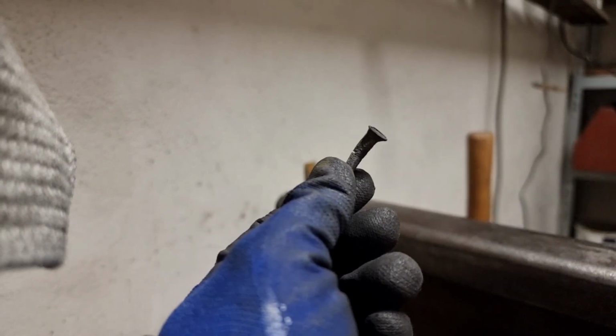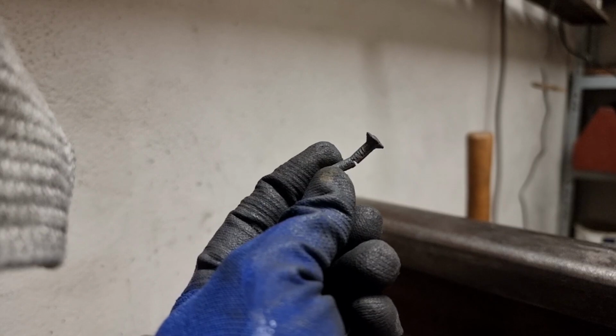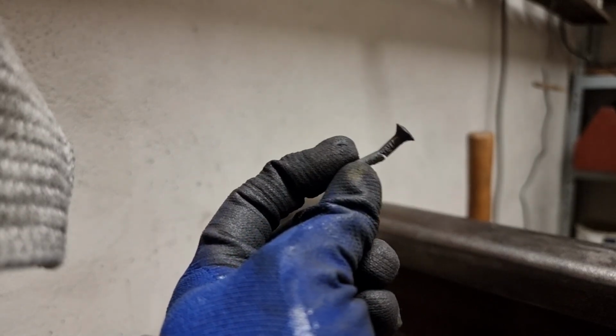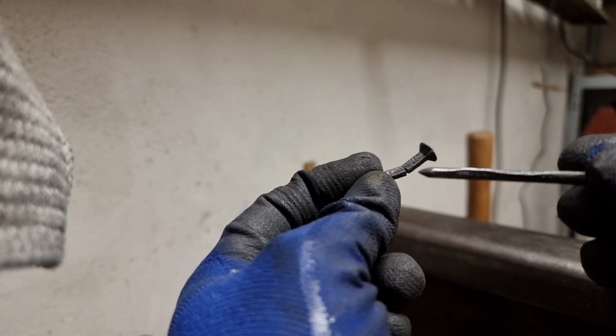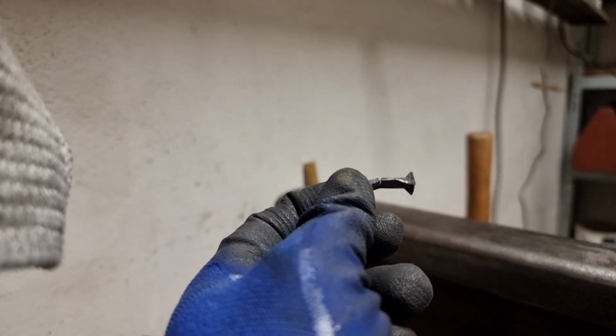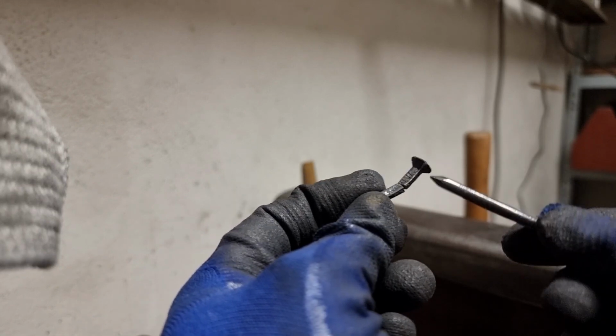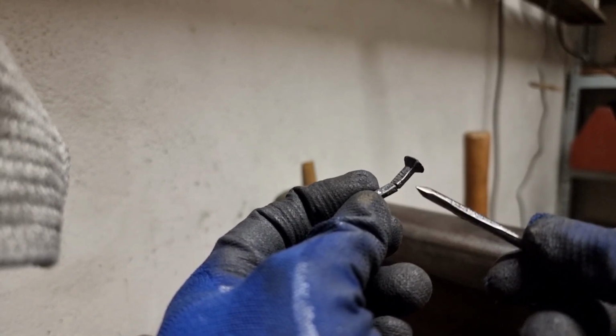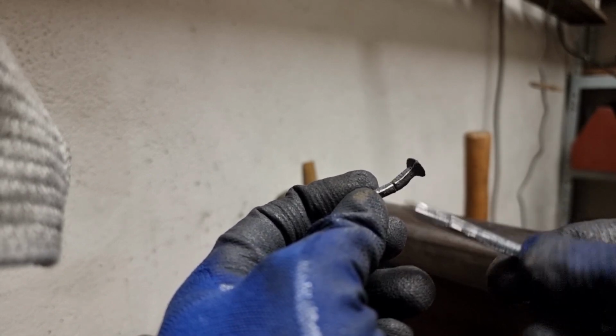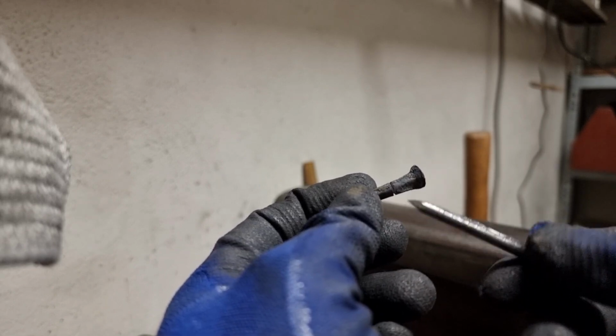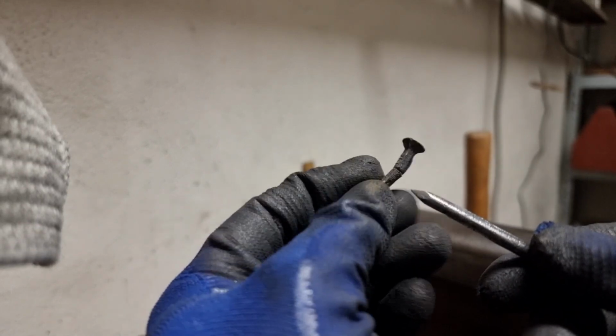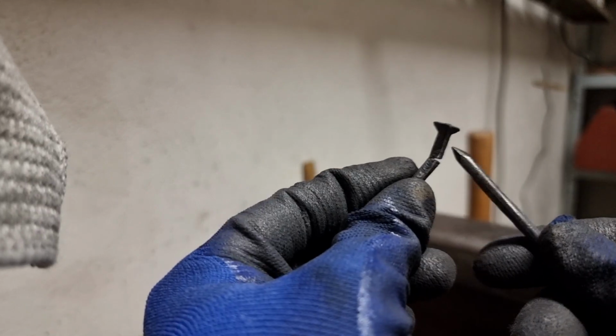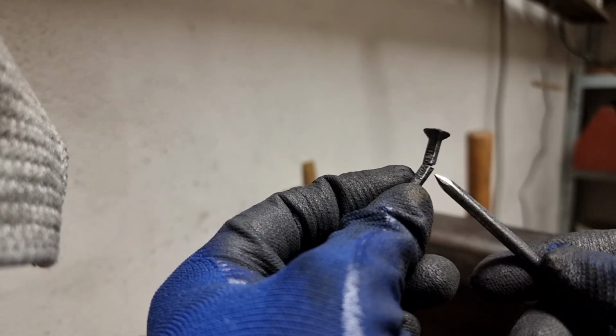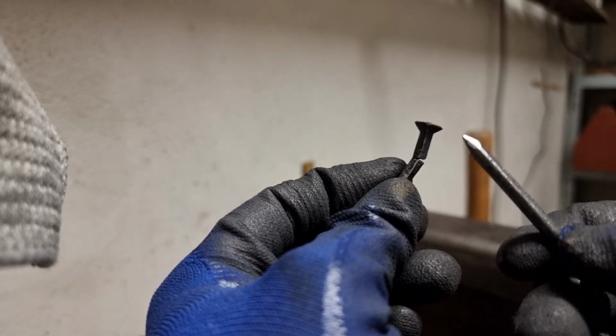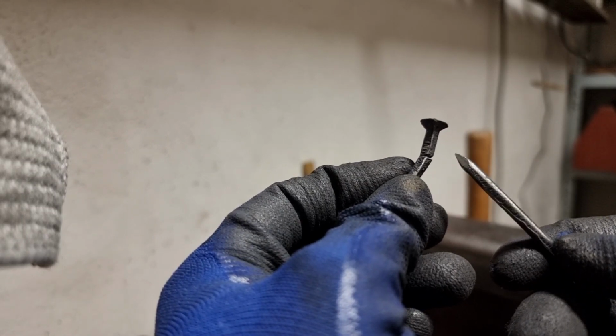And if you would keep that nail maybe for some hours more at that set temperature, 900 centigrades, then the diffusion, or the burn rate, it just depends on the time and the thickness of the material. So it's about 1 millimeter per 25 hours at 900 somewhat centigrades, yeah, 920 or so. It's about 1 millimeter per day. So we did 6 hours on that, so that's about 1/4 of a millimeter. And that is essentially the thickness that got converted to steel or a wrought iron, or at least a low carbon iron, no longer having the brittleness of our white cast iron.